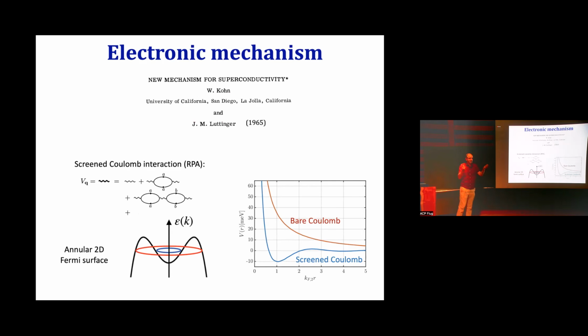Because the electrons that pair don't actually live in free space, otherwise they would never be able to bind. They really are binding on the background of this electron liquid, which is all the other electrons. Therefore, the effective interaction between two electrons close to the Fermi surface is not the bare Coulomb interaction, the 1 over R function of space. It's a screened Coulomb interaction, screened by all the other electrons. And this is the calculated screened effective interaction, on the background of other electrons forming a Fermi surface which has this angular shape.